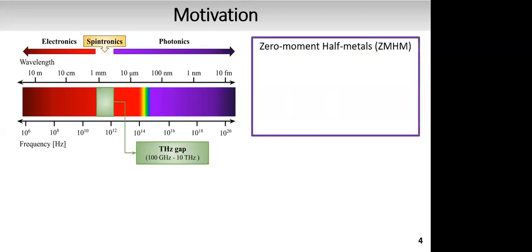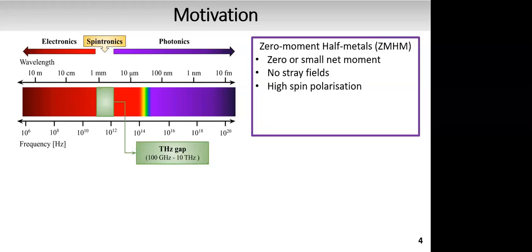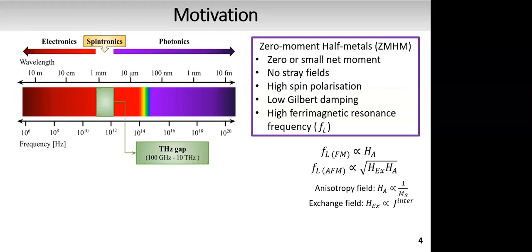So this material is ideal for this purpose because it has zero or small net moment, no stray fields, high spin polarization of Fermi level, low Gilbert damping, and also a high ferromagnetic resonance frequency. And we can distinguish two modes, the ferromagnetic one, which is proportional to the anisotropy field, which scales as 1 over saturation magnetization. So of course, as the net moment goes to zero, the anisotropy field goes to almost infinity. And then we have the antiferromagnetic mode, which is proportional to the square root of the product of the exchange field with the anisotropy field, where the exchange field is proportional to the inter-sublattice exchange coupling.